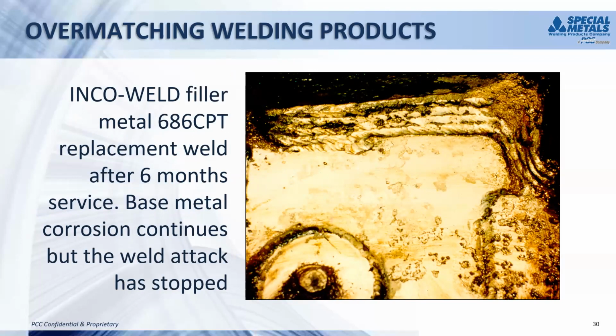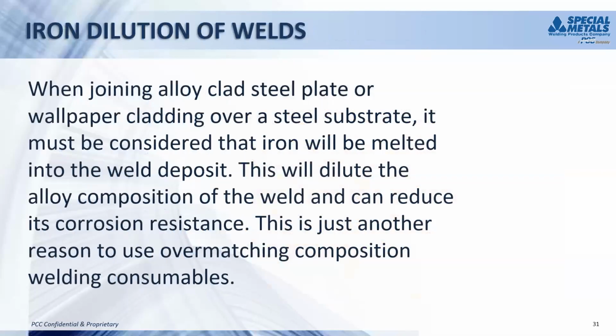So based on the result of the 4-sample test that we exposed, plus the performance here of the 686 CPT filler metal, that duct was relined with alloy 686 sheet, welded with 686 CPT filler metal, and the corrosion stopped. The next slide.